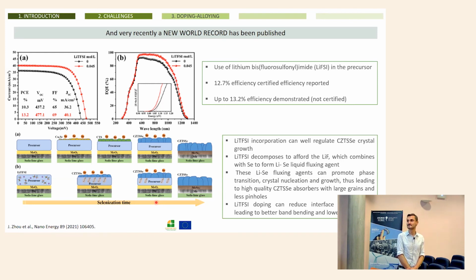And why open to new materials? You know, we are researchers, so we are always looking for something new. I was working on kesterite for 10 years. At this moment, the kind of things that we can do with kesterite start to be saturated, and we need new ideas, new materials. For example, right now, tandem solar cells are becoming extremely relevant because you can go to 40% efficiency maybe in the future. And antimony selenide and antimony sulfide are extremely interesting for that because you can produce them at relatively low temperature, at 300, 320 degrees, and then make them much more compatible with silicon than other inorganic technologies. For such applications they are extremely interesting.